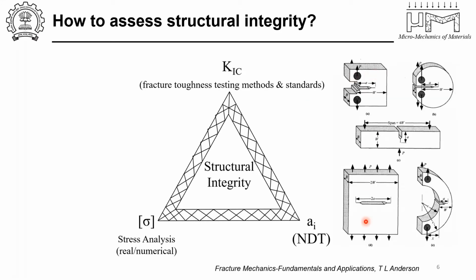And if you look at all the useful fracture toughness test geometries, they all have originated due to practical considerations of the material, right? We could have just one testing method, like you have in yield strength measurement. You do a normal uniaxial tensile test. But in case of fracture toughness testing, the origins are more practical, and people have come up with various geometries in order to not change the specimen, instead use the specimen configuration that is existing and measure its fracture toughness.